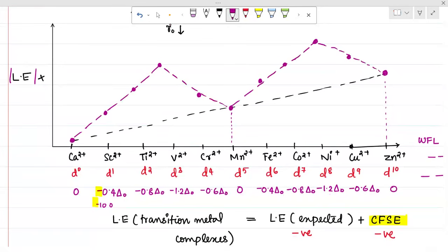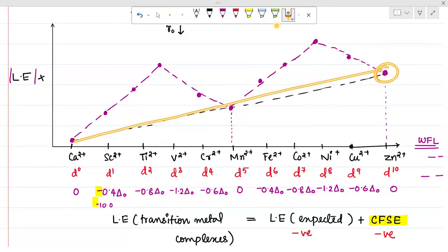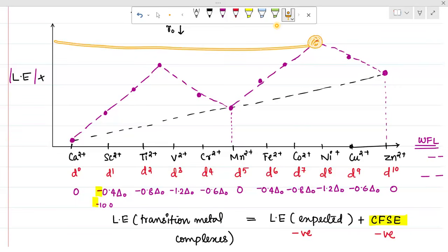Can you see the trend? This is the actual trend of lattice energy for the complexes of transition metals in +2 oxidation state with a weak field ligand, important, forming octahedral geometry. This is a trend. So if you just expect the normal trend, you feel that the highest lattice energy will be for zinc, because this is the trend that you expect. The stability of the zinc complex would be the highest. But actually, when CFSE is also considered, it's not zinc. You can see the highest point is for nickel. Nickel is the most stable one, right?